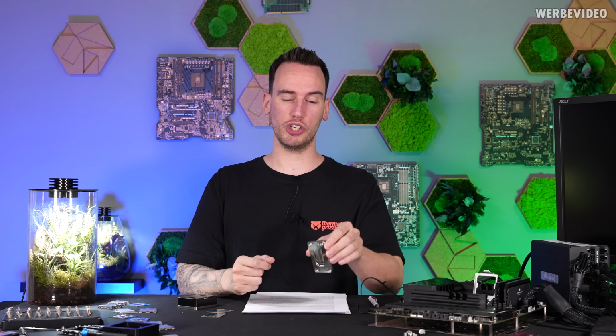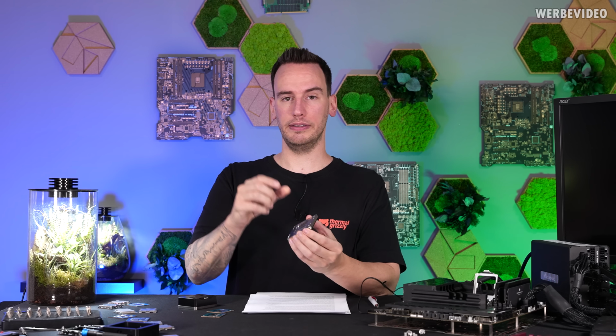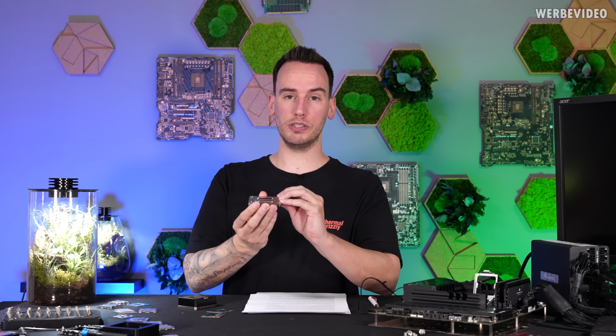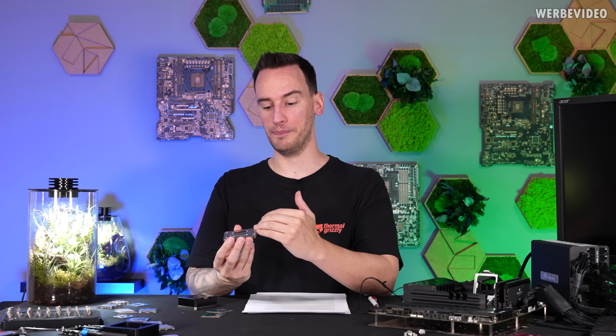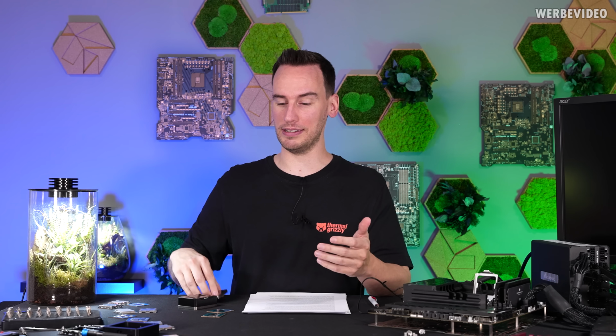The other process, as I mentioned, electroplating. Again, you take your piece of copper, put it in the solution, apply electric current, and this deposits nickel particles onto your copper. But it's quite different in how the layer looks. In the chemical nickel, as I said, it's an amorphous structure. In electroplating, it's a crystalline structure. A crystalline structure has a much less adhesion towards the copper. And this results in a higher contact resistance between the nickel layer and the copper. On the other hand though, electroplated nickel is like 99% nickel. And this results in a much higher thermal conductivity of the nickel itself. But as I said, you have a higher contact resistance between the nickel and the copper. So it's like a trade-off.